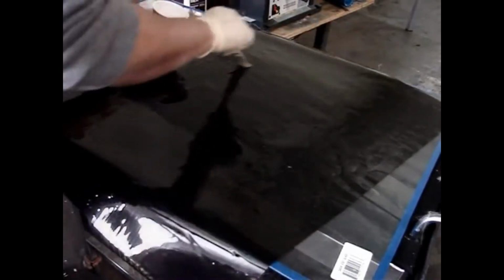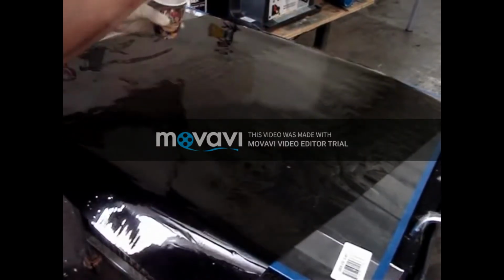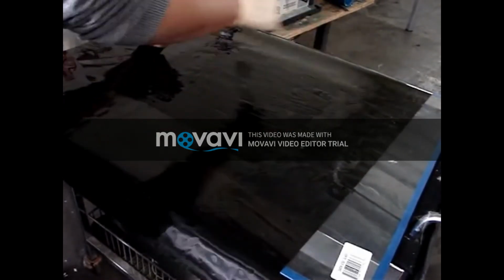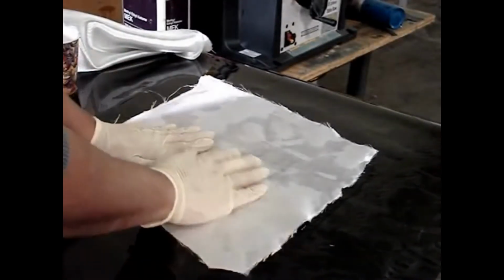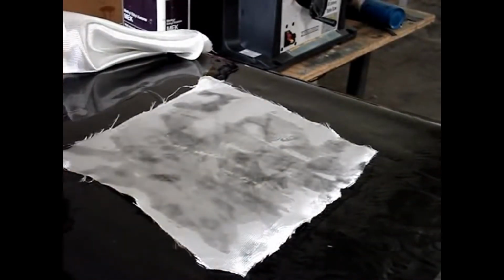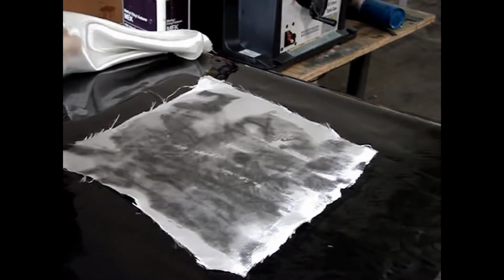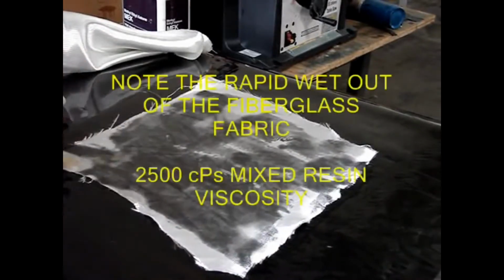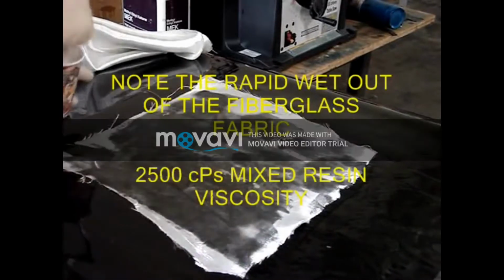Firstly, a 10 mil coat of impregnating resin is applied onto a 4 mil plastic polypropylene film as the carrier for the impregnated fiberglass. Before we continue, we have to take note that the rapid wet out of the fiberglass fabric is 2500 CPS mixed resin viscosity.